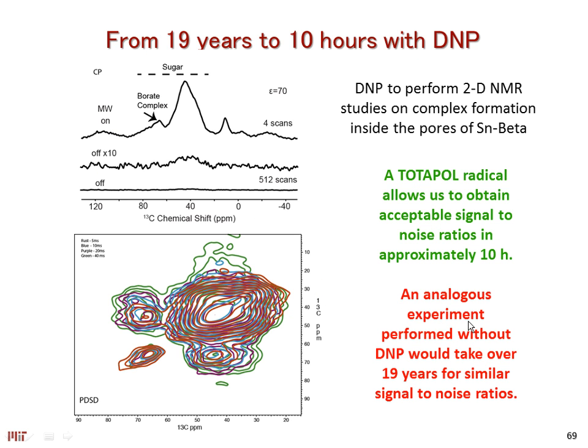So, for example, we use it to understand what happens inside of the pores of these zeolites when sugars are in there. You can do these 2D experiments, things that would take a ridiculous amount of time to get. Signal-to-noise ratios like this, for example, we can get in about 10 hours using DNP. And with this, we have discovered that sugars inside of the pores of these zeolites actually exist in the furanose form. For example, glucose in the furanose form is very rare in aqueous solvents, right? We have a very, very small proportion of that, but somehow inside of the zeolite, with these 2D experiments, we're able to confirm that it actually exists in the furanose form, and we don't quite understand why that is the case. So this is something that we continue to investigate.